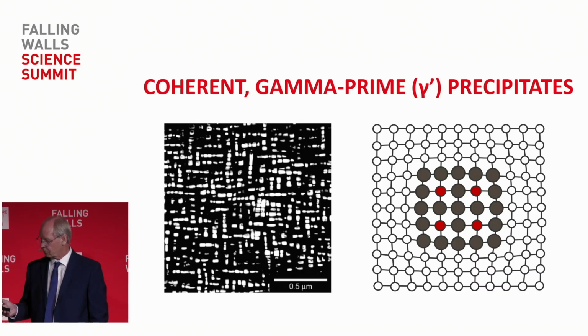It strengthens the material, and the key to the strengthening mechanism is that it aligns itself coherently, so the atoms align from the matrix. You can see in the picture on the right, they align with that ordered intermetallic gamma prime phase. So it's a very important phase in the development of superalloys in these applications.